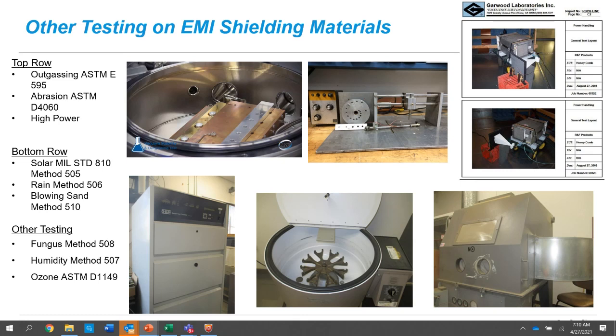So some of the different testing we do, outgassing is certainly a big one for aerospace and space applications, where you're looking at, in a vacuum environment, what comes off of this material. So there's usually two things that are measured: the total mass loss, so how much weight is lost during this exposure, and then secondarily what are called CVCMs, collected volatile condensable materials, that could then fog an optic. So usually in optical situations, in space situations where there's high vacuum, that's a consideration. So we've done a lot of testing on our materials, and for the most part, the polymeric materials perform well and meet the ASTM requirements.